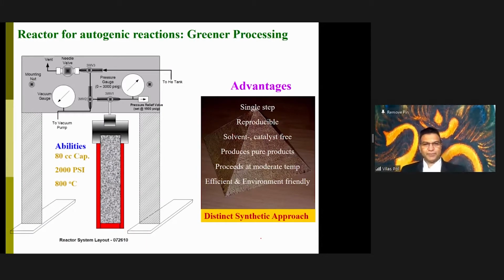So this is the reactor I developed during my research myself at Argonne National Lab, where it is considered a high temperature, high pressure reactor in order to make such unique material, and which has plenty of advantages instead of disadvantages. It is a single step process. Anybody can make it. You don't need a PhD to make the material. I don't use any solvent. Chemical engineering is known to use solvent and alcohols and this and that and distillation. I avoided everything. I just throw the plastic bag inside and heat it up and get the product as we need. We get a dry product, so we don't need to do any further processing or purification steps.